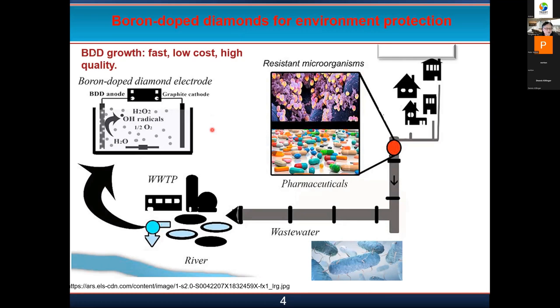Another application for boron doped diamond is that it can be used for electrodes to electrochemically or electrophysically kill the bacteria and the virus in water, which is important for environment protection, because we cannot release it to the environment without treatment. Otherwise, there's secondary contamination. So we try to use electrochemical approaches to disinfect the water. But the problem is that we need a diamond electrode, because it gives us stability and electric conductivity, and also the right match with the chemistry involved in the water disinfection.